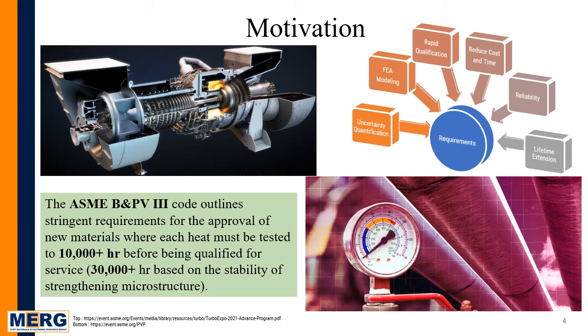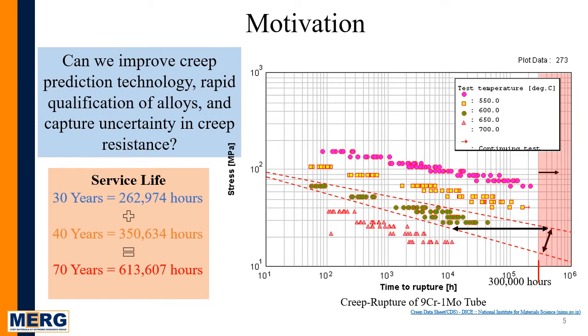For the newer candidate alloys to be in service, there is an extreme requirement by the ASME Boiler and Pressure Vessel Code that new materials must go through 10,000-plus hours of testing before being qualified for service. This is not impossible, but it is improbable for most cases, if not all. When in service, the power plant materials are susceptible to creep-induced failure. When creep is extrapolated to the low stress and high temperature regime, we can see substantial scattering, and this scattering in rupture life can persist across logarithmic decades.